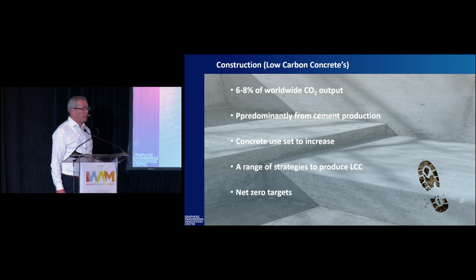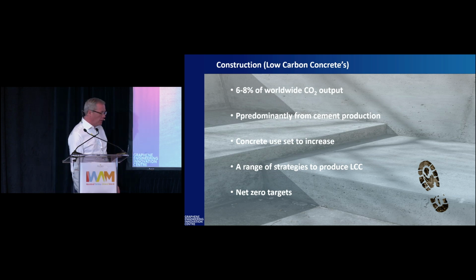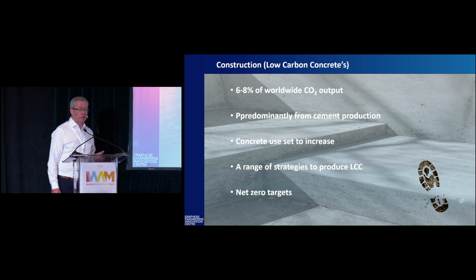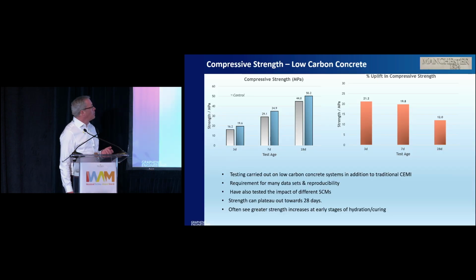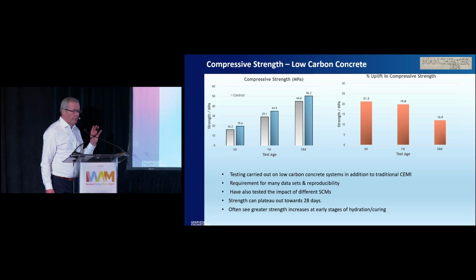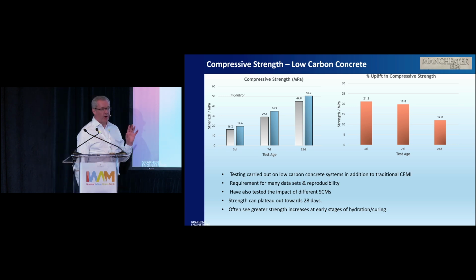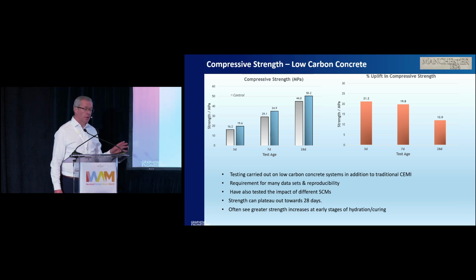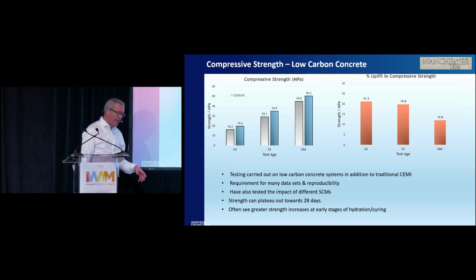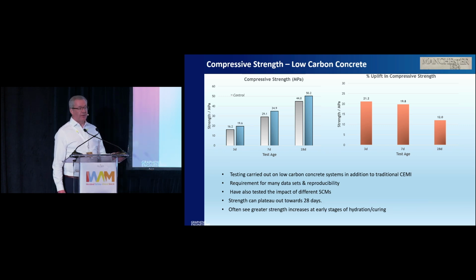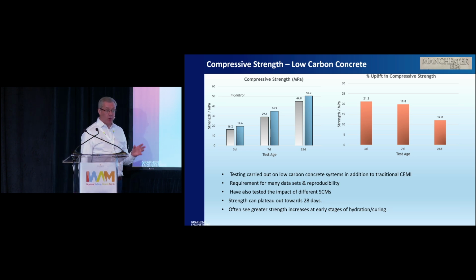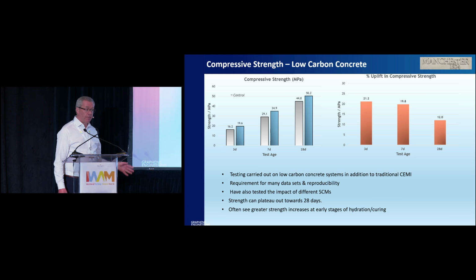But you can clearly see the worldwide drivers for net zero, especially when cement has such a high carbon content. Some of the trials we've done have allowed us to increase construction materials performance. We've worked with about 5 or 6 low carbon manufacturers, and they're using graphenes either as a dry dispersant or in a liquid dispersant as an admixture. There's been lots of publicized data, but the adoption by the supply chain has been quite slow because largely the results have not been replicated in the field.